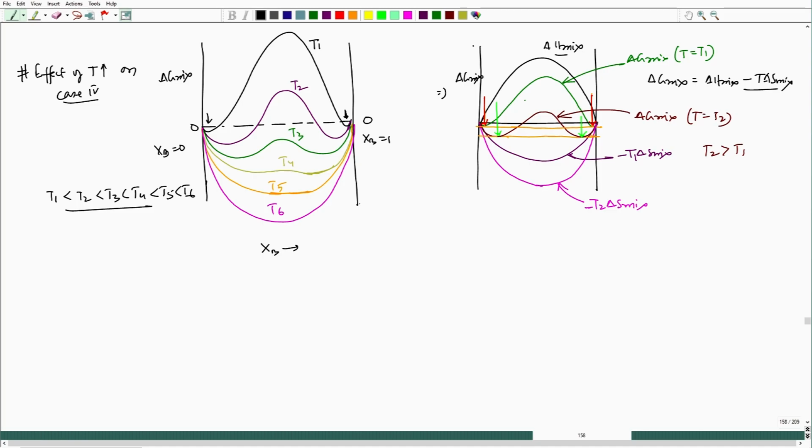So, if I see the common tangent, they are basically passing through those two minima. This is one, second one is this, third one is this, fourth one is this, fifth one is just one single point, and it is basically T critical, and the final one we have no inflection. This is belonging to a critical temperature, fine.